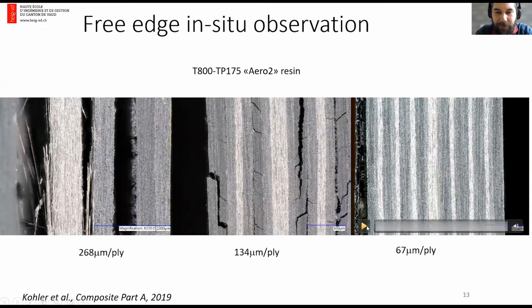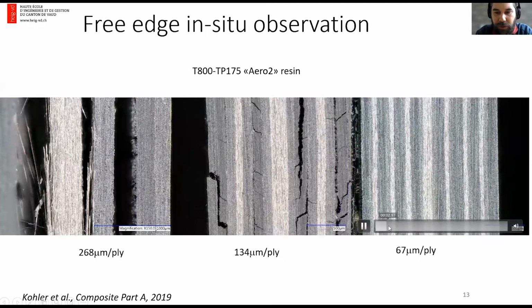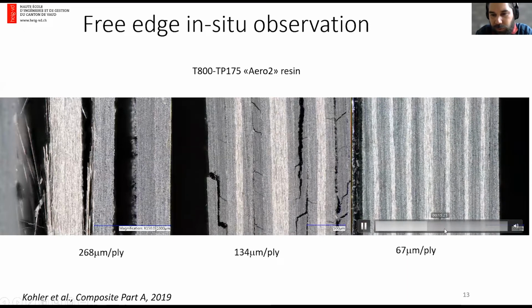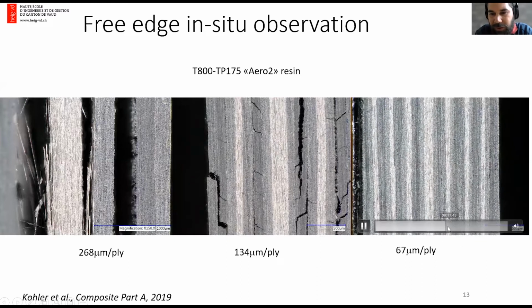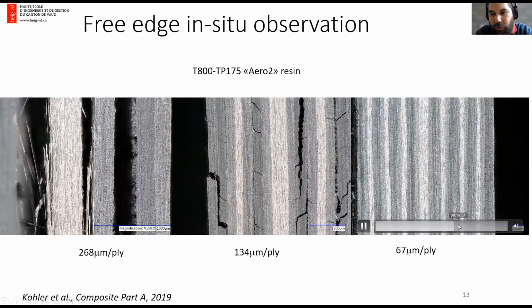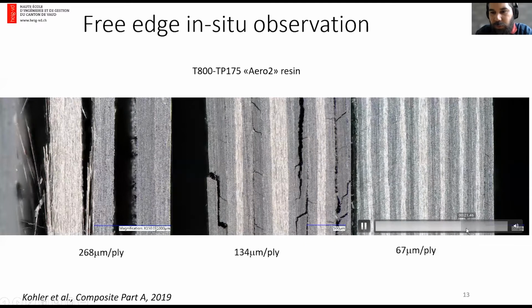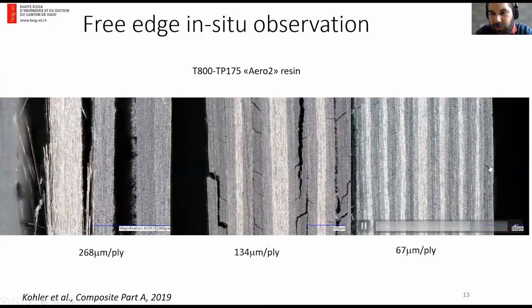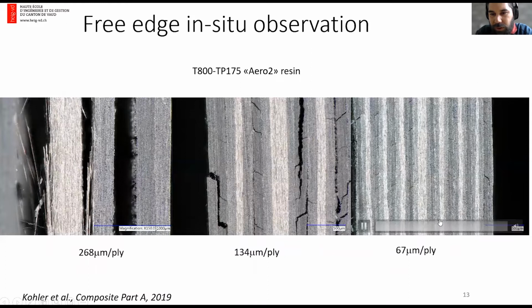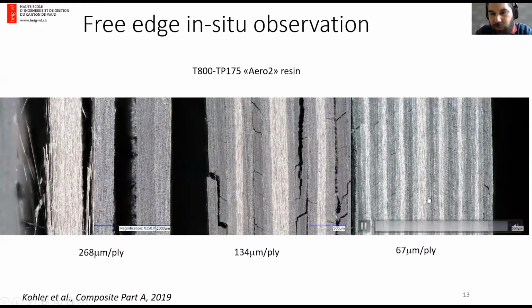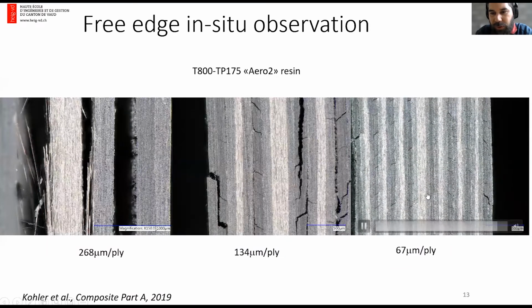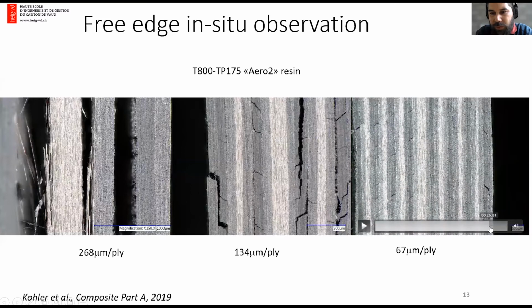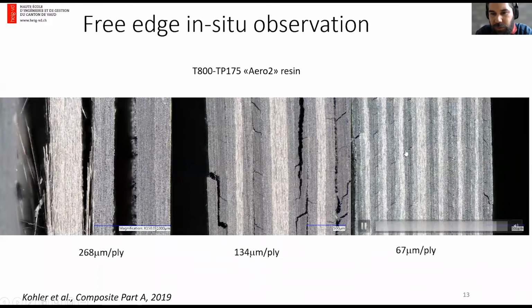And for the thinner plies, I will speed it up because not much happens. At more than 50% of the test, we still don't see any damage. Finally, we see some transverse cracks. And close to the end of the test, we see a very sharp increase in crack density of transverse cracks, as you can see here.